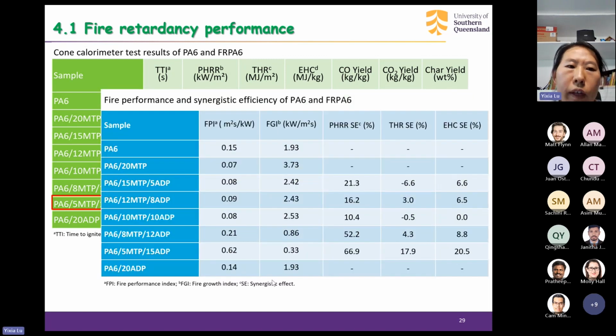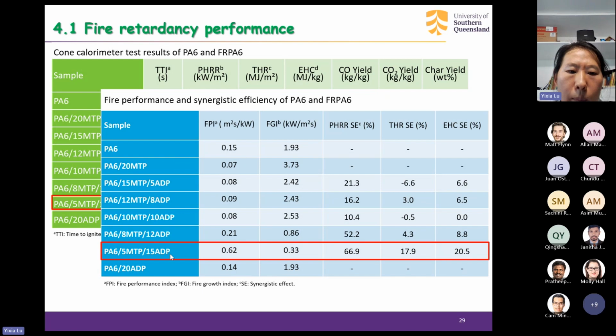And we also evaluate the fire performance and synergistic efficiency of these composites. We find that for PA6 with 5% of MTP and 15% of ADP, the fire performance index is highest and the fire growth index is lowest. And this composite possesses the highest synergistic effect regarding to PHRR, THR, and EHC. The value is superior.